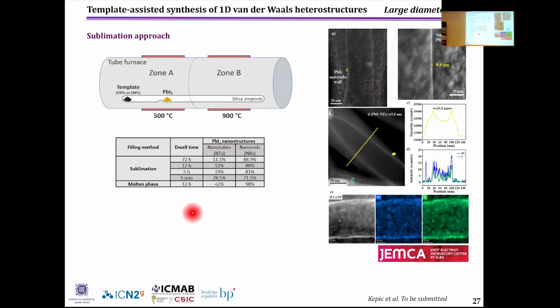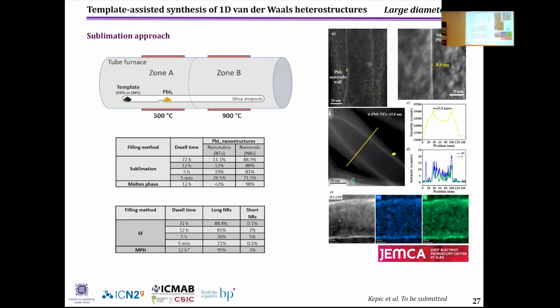Compared to the molten phase approach, we drastically increase the ratio between the nanotubes and nanorods, and confirm that fast treatment, I mean, in only 5 minutes, we can increase up to 10 times the amount of nanotubes we can encapsulate inside the fibers. And also, we were able to tune the length of the rods which were encapsulated inside.